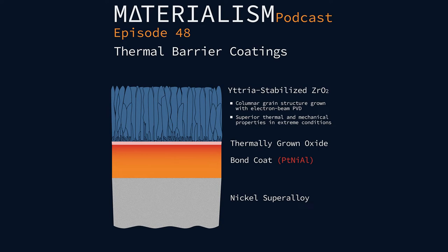The biggest benefit is that it is tolerant to lateral strain, which is exactly what we need, because the metal underneath it is going to expand at a different rate than the ceramic. And since you have a bunch of these columns which are technically separated one from another, you've built in a material that has a ton of cracks right through it, and so it is compliant in the lateral directions. That's a big deal.